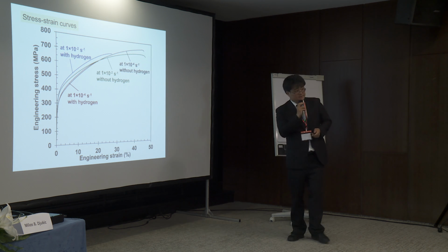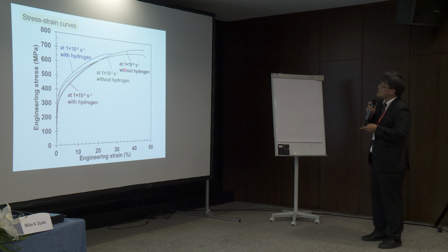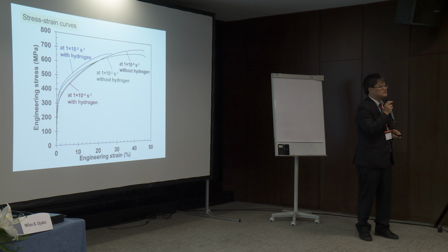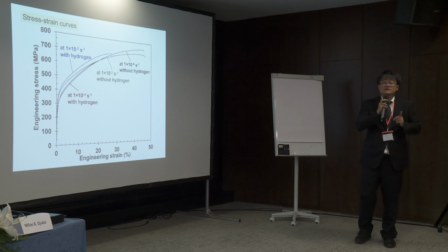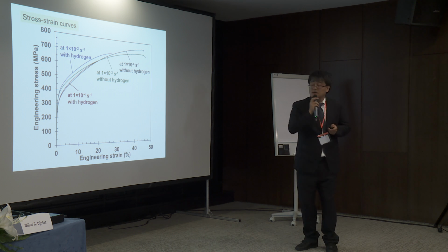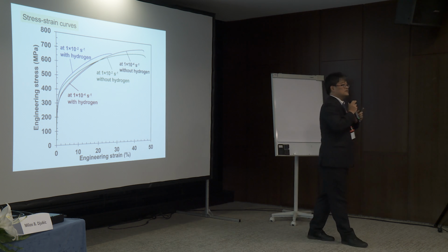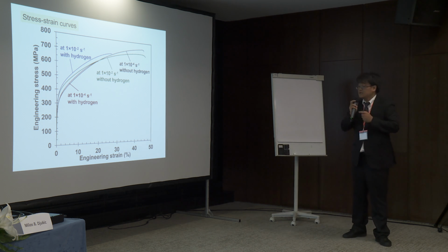Then this is the result. Even with hydrogen, the failure occurred after 18%. Okay, it's a significant plasticity. Then the point is what happens during 18% plastic strain with the presence of hydrogen and epsilon martensite.